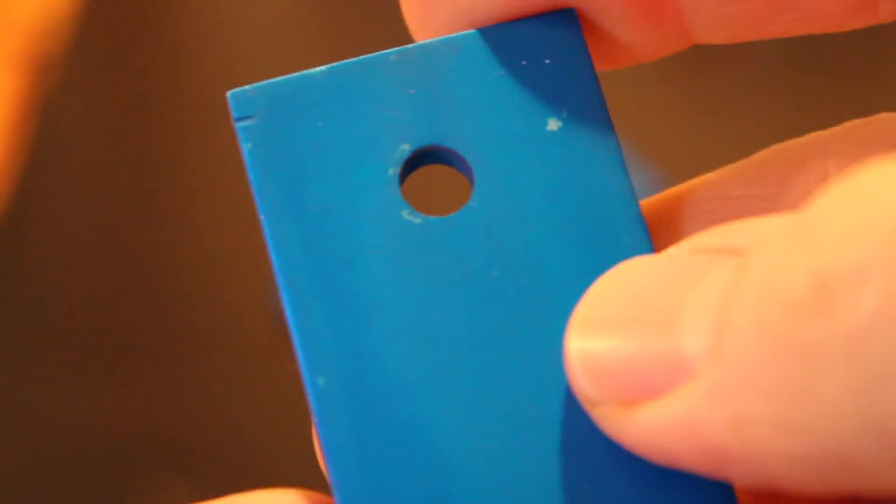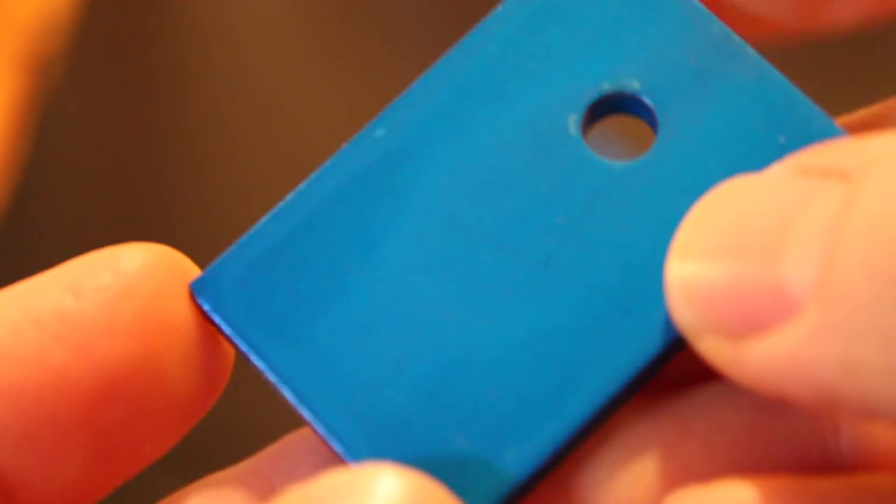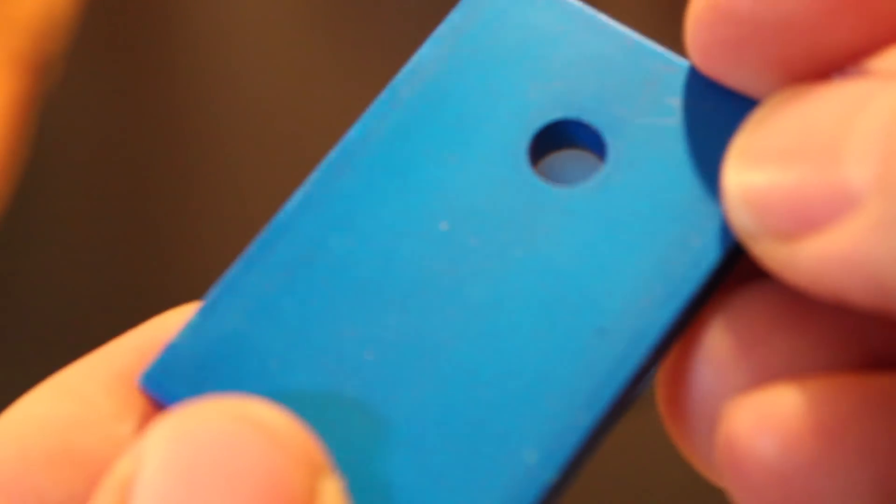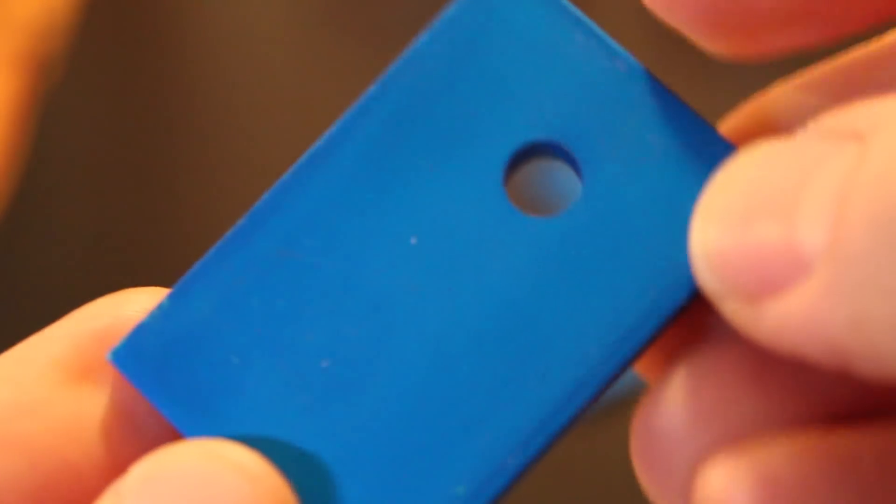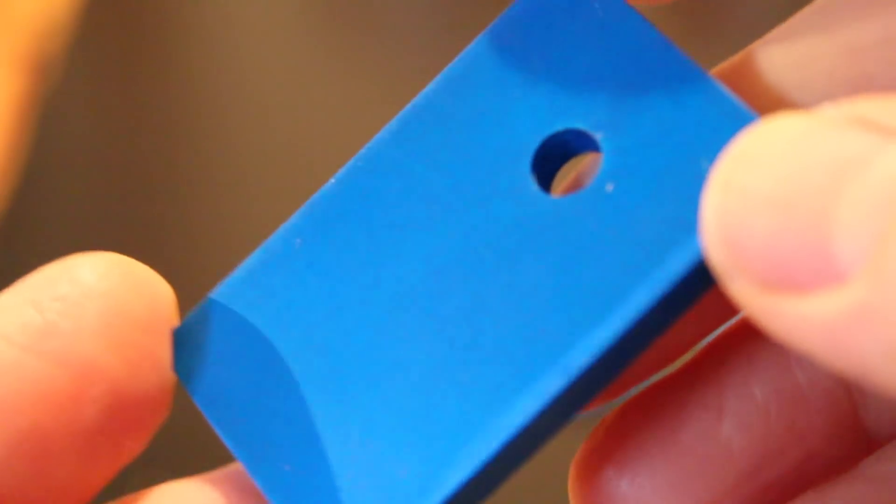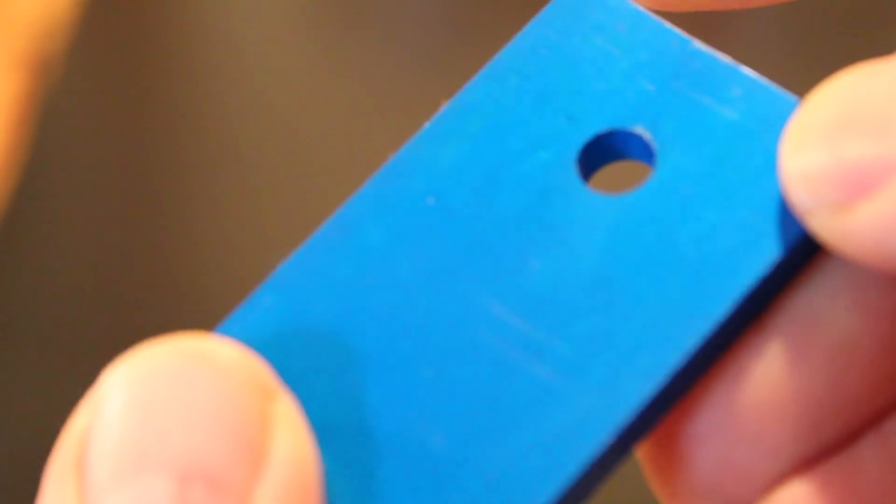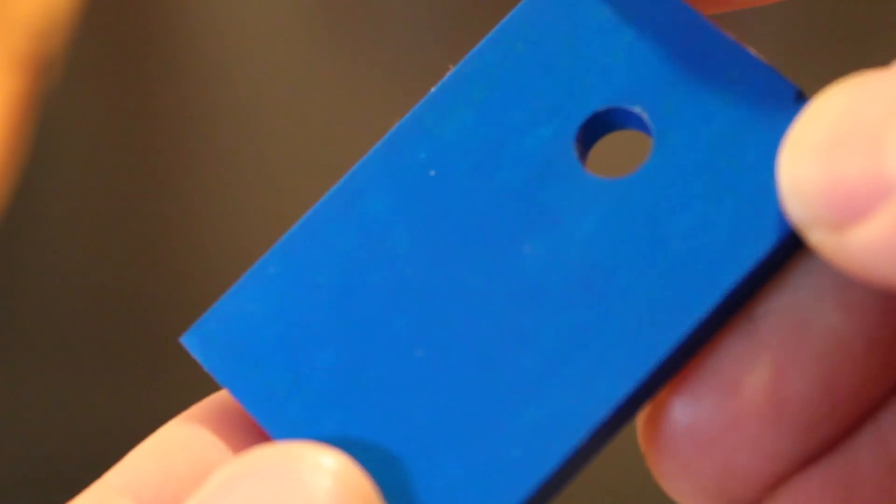And here they are the finished samples. These are the very first two that I did. You can see there's little imperfections in the surface, but the dye took very well. So I'm assuming that the anodizing also went well. On these first two I didn't do any sanding. I just cleaned with the acetone and isopropyl alcohol. So you can see that the surface is pretty even but also lusterless.